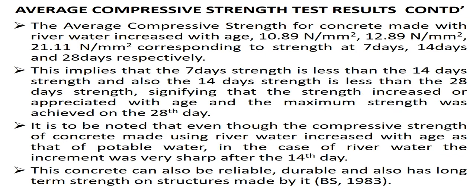The average compressive strength for concrete made with river water increased with age: 10.89 Newton per millimeter squared, 12.89 Newton per millimeter squared, and 21.11 Newton per millimeter squared, corresponding to strength at 7 days, 14 days, and 28 days respectively. This implies that the 7-day strength is less than the 14-day strength, and also the 14-day strength is less than the 28-day strength, signifying that the strength increased or appreciated with age, and the maximum strength was achieved on the